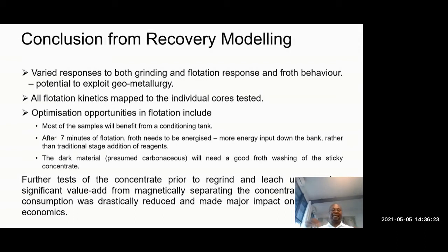So once you insert magnetic separation after you've collected the flotation concentrate, you reduce the mass of the concentrate, number one. But more importantly, that material, a lot of magnetites and some other material, when finely ground, accounts for almost half of the subsequent cyanide consumption that you were going to use. That was fantastic, because it adds huge value in terms of reducing your subsequent cyanide consumption for the leaching.